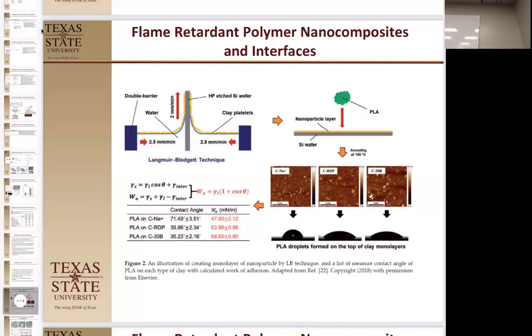And these are perfectly structured because you're actually measuring the surface tension change. You get what are called isotherms, which is a graph that tells you exactly how fast to move your walls. Once you get that, you can do different things later on. What we're looking at is layering clays on there, one plate at a time, so they get a perfect layer. When you take it out, you have this nanoparticle layer on your surface.